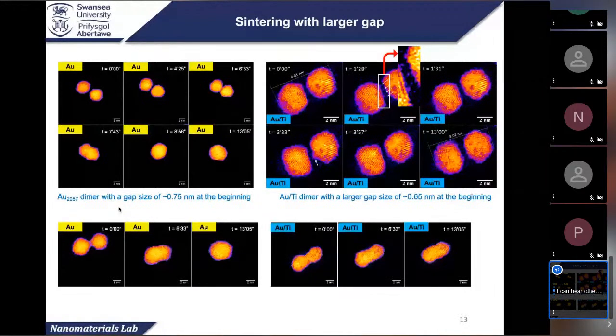Here's another case. Basically, those two particles are already connected with each other before the electron irradiation. For the gold, there's no surprise; they just become one particle. For gold titanium, even after 13 minutes, there's atom diffusion, but the particles try to hold their positions and try to resist the sintering. So we found that the gold titanium cluster shows a strong anchor effect against sintering.